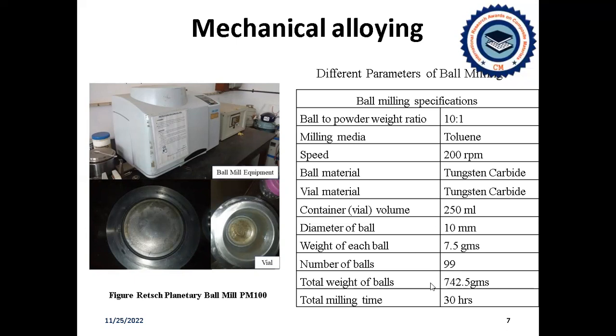These are the ball milling specifications. The table shows the ball milling specifications. Ball to powder weight ratio is 10 to 1. Milling speed was around 200 rpm. Ball material and vial material are the same, tungsten carbide. Container volume capacity is 250 ml. Each ball diameter is around 10 millimeter, and the weight of each ball is around 7.5 grams.